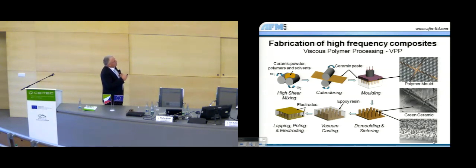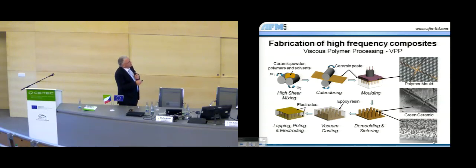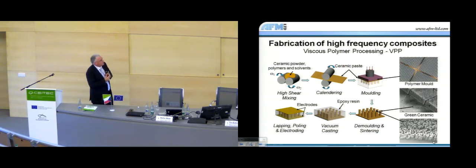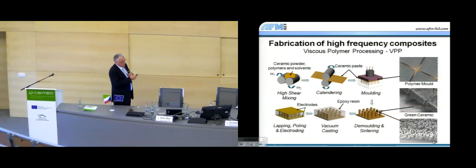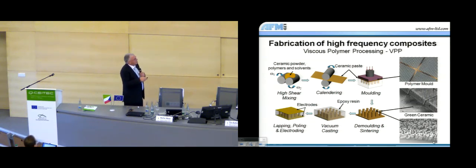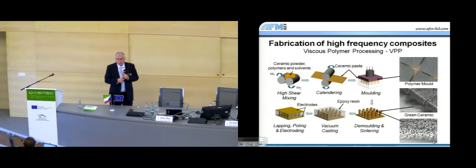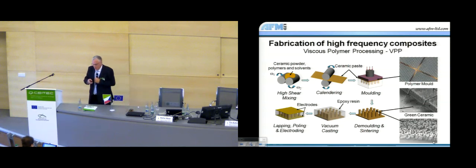In our particular case, though, what we're interested in is making pillars of this sort of structure. So these are about 20 microns in size, about 120 microns tall. So these are structures you probably couldn't machine very easily, or impossible to machine, we think. You have to make them by some other technique. But the molding also opens up some new exciting areas. This is what we've called a random structure. So this is still a pillar type structure, but randomized in its sort of latitude. And this gives some increased properties or better properties for the device. And this is a patented area of technology that we think is key to what we're trying to do.